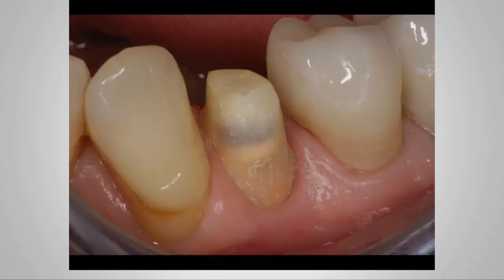This is another preparation on a lower bicuspid. The reduction is appropriate. It probably could use a little more anatomical reduction in the center of this area, even though I think you have at least 2 to 3 millimeters of clearance here. The margin is also something you'll need to think about with zirconia. Even with the more translucent zirconias, you're going to see the margin if you get some recession. The crown beside this is a lithium disilicate crown, and you'll see that the blend of the ceramic will be a little bit better than the blend of zirconia at the margin.